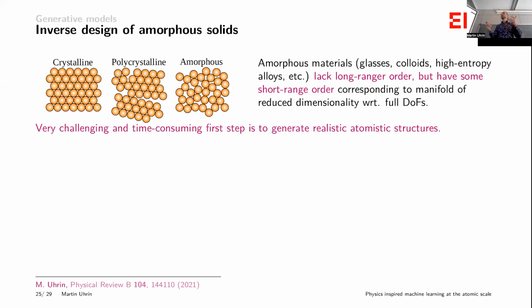There is some statistical correlation between where the atoms sit next to each other. Now, just as an experiment, actually, I was being shown one yesterday. One of the ways that we do this computationally is that we have to do effectively simulated annealing, right? We have to heat up our material and then quickly quench it at some quench rate to try and freeze it in an amorphous structure that we hope is stable.